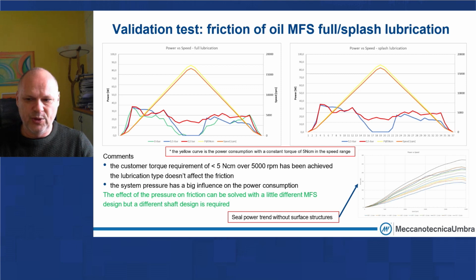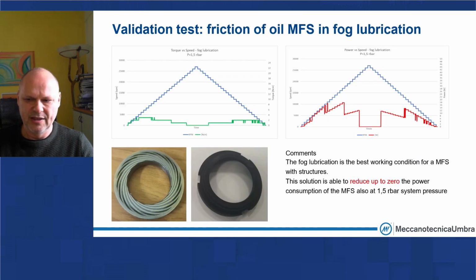In addition, we can see that the power consumption in splash and full lubrication is around 40 watts at every speed. In fog lubrication, we don't exceed 20 watts, and when we increase the speed, this power consumption decreases much, close to zero when we stay over 20,000 RPM.